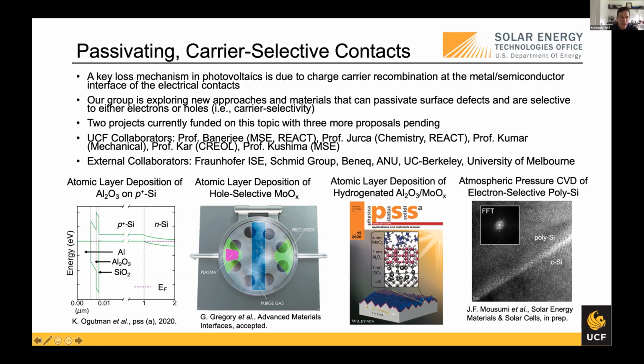And to give you an idea of some of the different flavors of these passivating carrier selective contacts, one thing that we looked at is using atomic layer deposition, which is a process that in particular, Professor Banerjee and Professor Jurca's groups are really effective at doing. So we've looked at using aluminum oxide, like only 1 nanometer, 1.5 nanometer of aluminum oxide to passivate the surface states at the silicon wafer. And then we can basically get tunneling through these layers into the contact there.